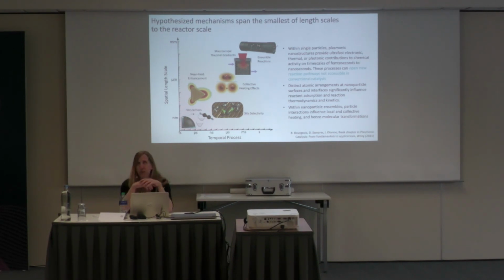In both cases, you can almost think about either palladium or palladium hydride as being effectively equivalent from a dielectric or refractive index point of view when we're at visible wavelengths. So that gap mode remains pretty much the same. It shifts by a few nanometers. Yeah, thanks. Really great question. In both cases, they're both metals at those frequencies. So that's probably the easiest way to think about heuristically why the resonance doesn't shift that much.